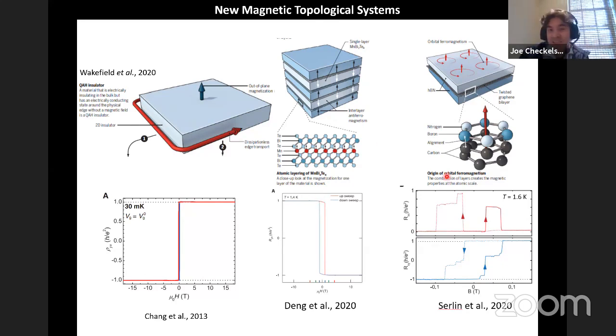In the same issue, as it turned out, there was the same kind of realization of the quantum anomalous Hall effect, but you could not get a more different magnetic system. And this is twisted bilayer graphene, which is next to hexagonal boron nitride, where magnetism arises not from local moments, but so-called orbital ferromagnetism. And in this case, again, you get this quantum anomalous Hall effect.